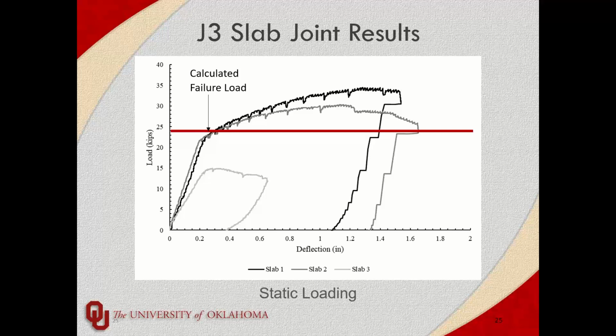If you've ever seen UHPC, it kind of flows like putty that just never stops, and it tends to wrap around things very easily. And then the steel fibers were able to help mitigate those micro cracks that you'll get once you start putting concrete in tension. And I think all of that combined really improved the bond behavior, even with a lower compressive strength. And so I think it's a good sign. It may show that while compressive strength is really nice to have in a lot of applications, whenever you're looking at bond strength or using shortened development lengths or really small areas for repair, you don't have to demolish near as much and still get developed rebar from a smaller section, even with a smaller compressive strength like you see with J3. Next slide.